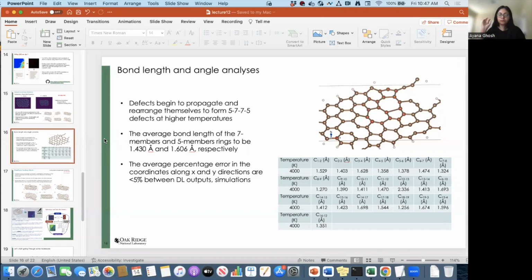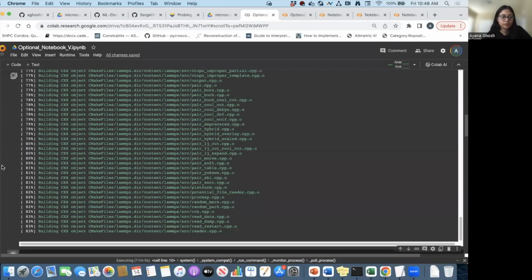So that way you can track which atoms have really participated in the reconstructions. For the geometry optimization, we performed multiple optimizations. Because we terminated the atoms with hydrogen, we kept the hydrogen atoms fixed and did the optimization on the carbon atoms only, in the XY plane differently, like running selective dynamics and things like that. So that information is also available.